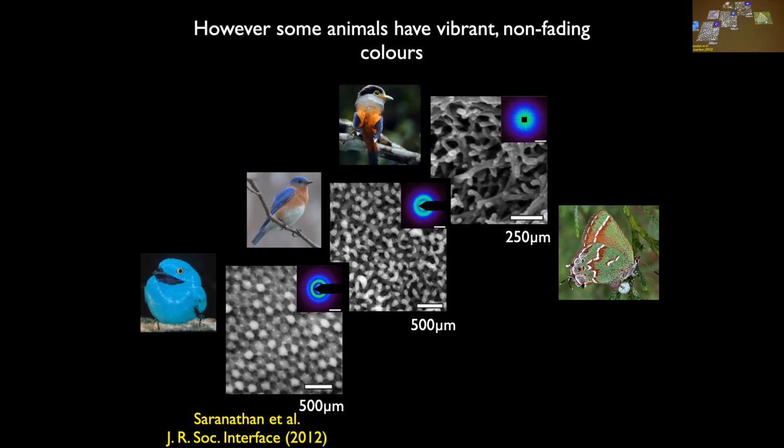But the point here is that all of these structures are almost in the middle of the wavelength range of visible light. So light will come in and bounce off, and basically the way it interacts with the structure actually gives us the color. So there's no dye involved at all. It's just from scattering with a structure that has a very well-defined wavelength. And you can have different types of structure. So now in this one, you have air bubbles, basically, in keratin. In this one, if you know what spinodal decomposition is, or a bicontinuous structure, this is a spinodal-like structure where you have a network that's connected together instead of bubbles. And then up here, you have something that's a little bit more random perhaps. So a couple of things to say is that this is actually interesting because all of these three structures are made of the same material.